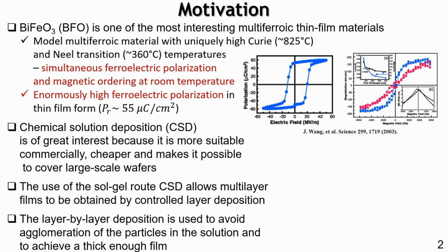Why is chemical solution deposition an interesting technique to produce BFO? Because it is a really easy and cheap method, which allows strict stoichiometry and allows creating large wafers. Large wafers are really interesting for commercial applications, in comparison to PLD or other deposition techniques such as magnetron sputtering. Chemical solution deposition allows creating a homogeneous film over a large wafer size.